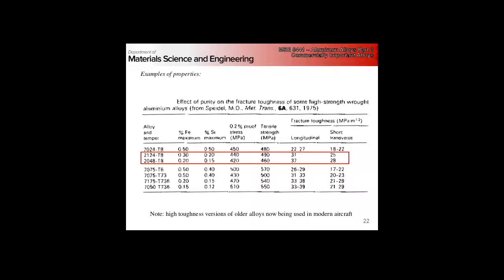Our strength doesn't change, but we can get very large increases in the fracture toughness. If we look at 2048 versus 2024, we get very large gains and we approach what we get for the 7000 series, with of course 7000 being much more expensive than 2000.